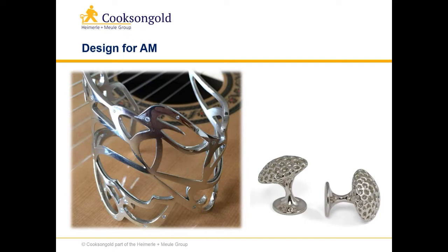We think the reason why platinum works so well is because there's a limited number of elements inside the actual alloy. In this case, it's just platinum ruthenium, whereas in the gold alloys, for instance, you have gold, silver, copper, zinc, tin, and those elements make the parameter development slightly more challenging in terms of the development work that we've had to do. Yeah, platinum produces beautiful parts.